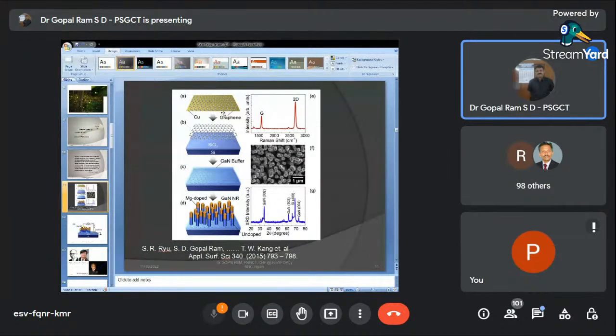So it can be floated on some copper etchants. Then the copper will be etched out. Now this graphene alone will be floating like a net. Then it will be fished out onto the silicon dioxide substrates. Now we have a conducting layer on this silicon dioxide substrate. Usually to grow these gallium nitride materials as a single crystal, we need another hexagonal buffer layer. Fortunately, this graphene also is a hexagonal material.